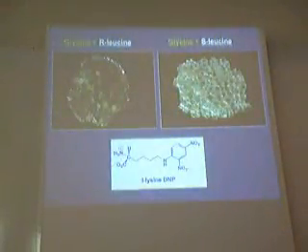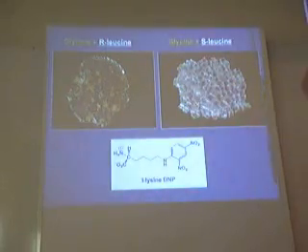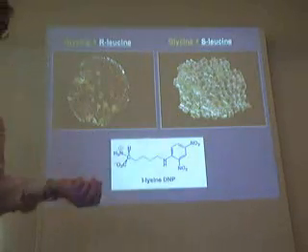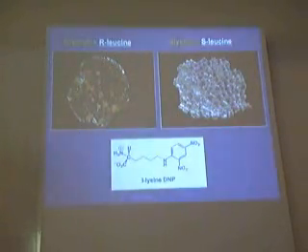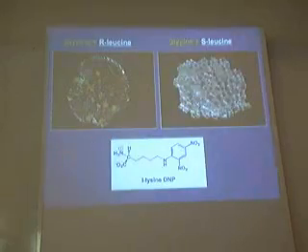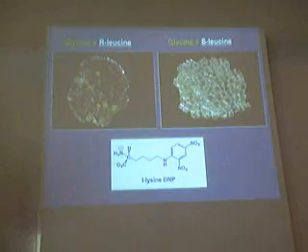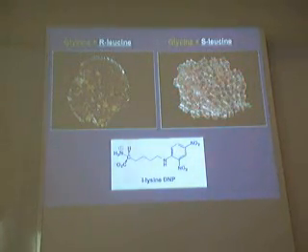But we can see that we can perform an experiment of the separation of the amino acid, which has the two elements of the Frank model. The molecules formed at the air-water interface form clusters which enhance the crystallization of the glycine crystals with the appropriate orientation, whereas the one in excess in solution prevents the growth of the other, and maybe there is also some Ostwald ripening, because these crystals are quite small, and maybe that can also assist. So this is a kind of Frank model experiment, which expresses the separation of the DL amino acids. Okay?